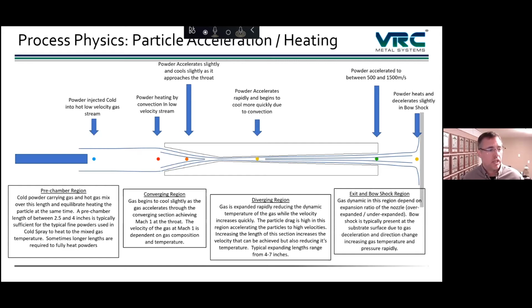So positioning of that pre-chamber and the injection tube, there's several different applicator designs that are used to achieve different preheating distances. Then the gas goes through the converging section, through the throat of the nozzle, and then starts to expand out through the diverging section, which is where the gas goes supersonic and the particles really start to accelerate.